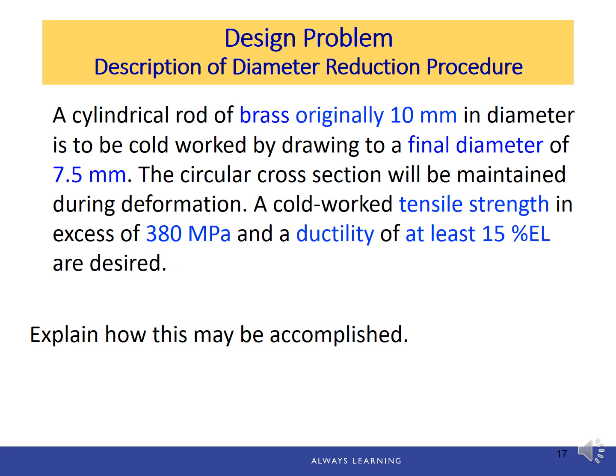Let's see one design problem to see how to use the concept we just learned about cold working and also heat treatment to achieve the desired property for a given material. We have a cylindrical rod of brass originally 10 mm in diameter, which is to be cold worked by drawing to a final diameter of 7.5 mm. The circular cross section will remain during deformation. A cold worked tensile strength of at least 380 megapascal and a ductility of at least 15% in elongation are desired. So explain how this may be accomplished.